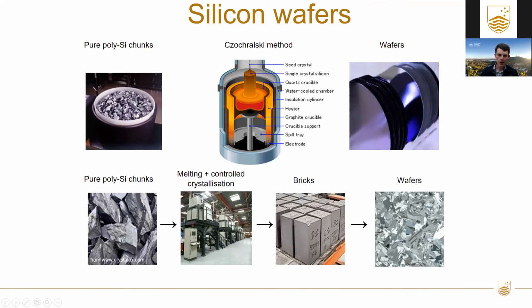So we start off with a hyperpure silicon. This is a material that has been taken from raw sand, stripped of the oxygen, and then purified through a chemical process. And then we melt that within a quartz crucible, so a silicon dioxide crucible, again to minimize contamination. And then we introduce a seed crystal. We just have a crystal of silicon, which has a known orientation, and we dip it into that melt. And then when we slowly withdraw it from the melt, we can grow a single large crystal of silicon from that melt.